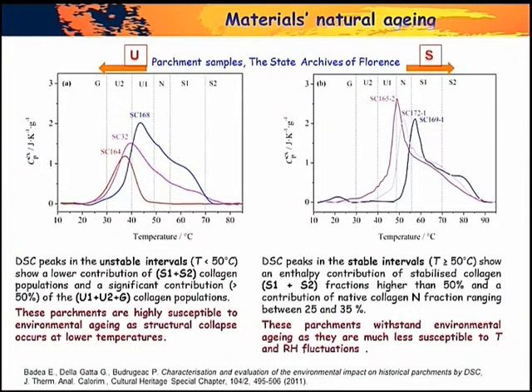We can say that parchments can be classified in these two groups: stabilized parchments, where the contribution of the stabilized collagen is higher than 50%, and these parchments, as you saw in a previous slide, have the tendency to withstand higher values of temperature and relative humidity, as well as relative humidity fluctuations, while the other group of parchments, where the most significant contribution comes from the unstable collagen, pre-gelatin and gelatin, are highly susceptible to environmental aging. As you can see from their temperature, they can collapse at room temperature, and especially when in moist condition.